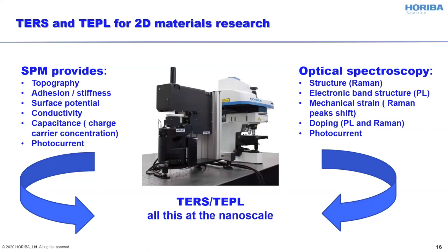When we combine these two lists together in the form of TERS and tip-enhanced photoluminescence, we can do both of these lists at nanoscale. And this is really important because many heterogeneities that we observe in two-dimensional materials are really of nanometer scale and cannot be probed with conventional optical spectroscopy, which has a natural limit of the wavelength of light, which is about a few hundred nanometers.